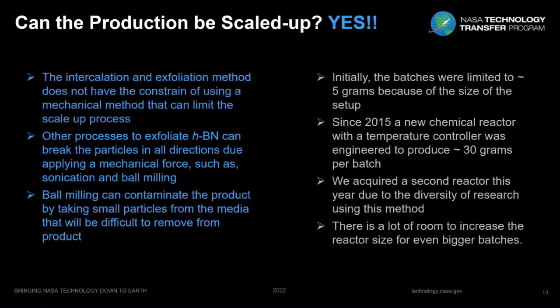Can the production be scaled up? Yes. But let me first mention some of the advantages of our technique. The intercalation and exfoliation method does not have the constraint of using a mechanical method that can limit the scale-up process. Other processes to exfoliate hBN can break the particles in all different directions, and that's not what we want. This can happen by applying mechanical forces, such as sonication or ball milling. Ball milling can contaminate the product by taking small particles from the media that then will be very difficult to remove from the product. These mechanical methods might be more difficult to scale up.